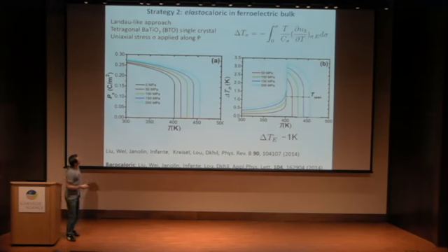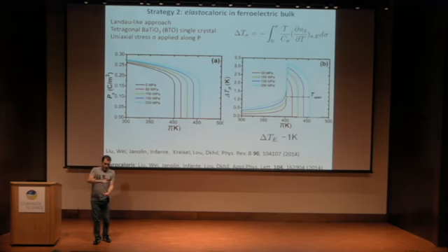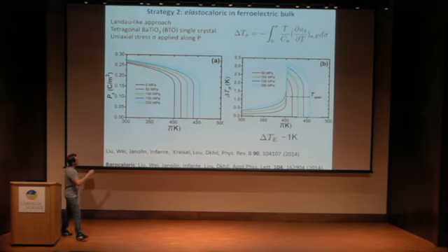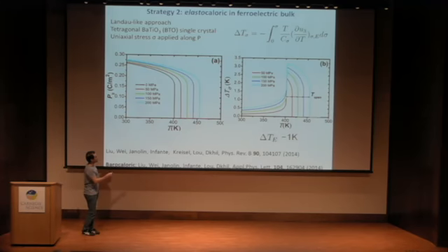So I have to be faster, so let me go faster. There is another way, as I told you, which is to use this strategy through elastocaloric properties. So this is, for instance, polarization as a function of temperature, just a calculation from a Landau-Ginzburg-Devonshire approach. We have a BTO single crystal, and then we pull the system at different pressure. So sigma here positive, different pressure, and you see that we can shift this critical temperature. It means that if I am here in the black curve without any pressure, the polarization is 0, and when I apply this pressure, the polarization from 0 becomes non-zero.